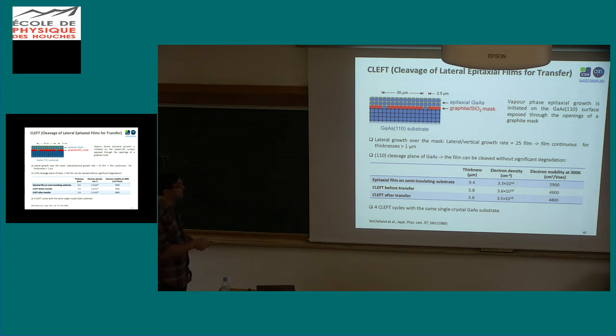This is the reference grown on a semi-insulating substrate. You have the mobility here, which is quite good. And then you do the same with this cold cleft process. So before and after the transfer, the mobility is really very, very similar. Actually, the transfer at this point you can do only mechanically, because once again, the III-V is stuck to the substrate through the opening, but here it is basically van der Waals adhesion. So you can manage to remove it mechanically and possibly reuse the substrate a certain number of times.